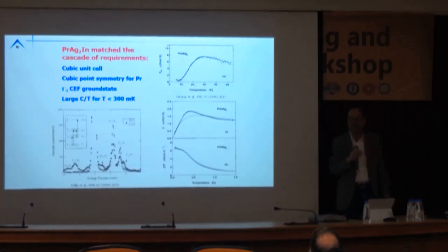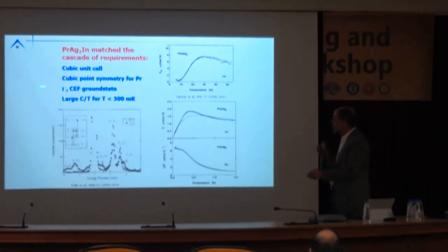Thank God for proceedings and people taking time writing it up, because their failure was exactly what we were looking for. We were able to reproduce their inelastic scattering results. You have a gamma 3 doublet separated by 6 meV, 60 Kelvin, from the first excited state. We can take these states and compare it to a specific heat, take the distribution of Schottky anomalies, and it fits the data beautifully. At low temperatures, we can look at the specific heat, and below half a Kelvin, it rolls over and goes linearly through 0, which in plot C over T versus T rises and saturates above 6 joules per mole K squared. If that's electronic, this is a very heavy, heavy fermion.